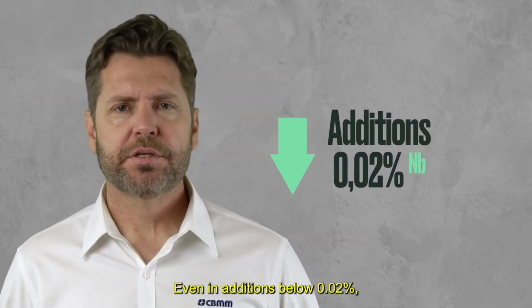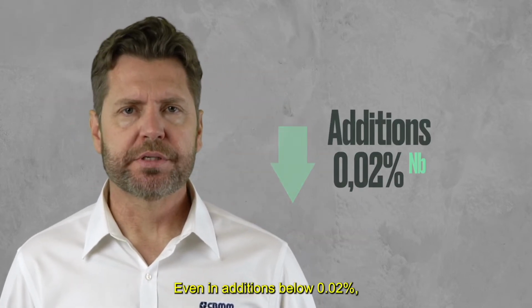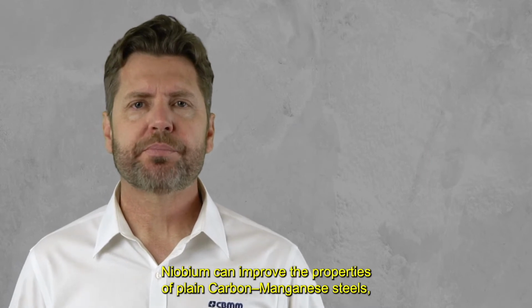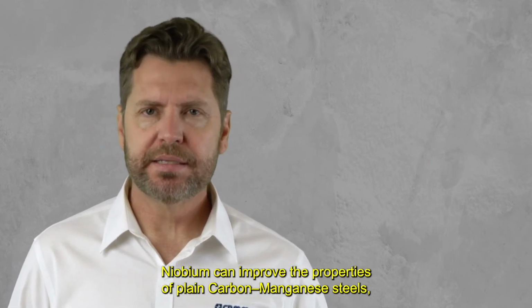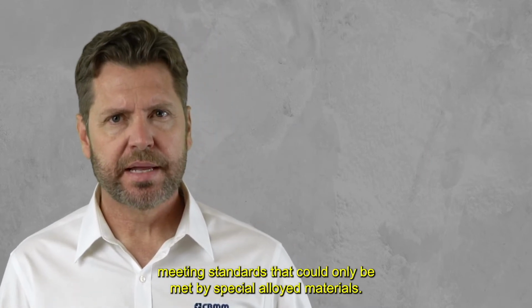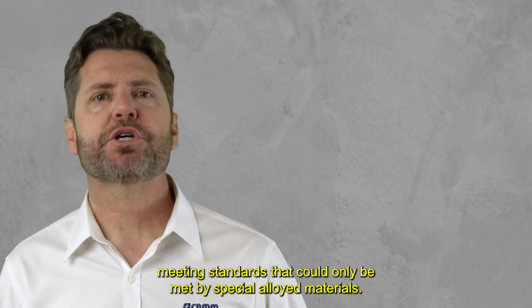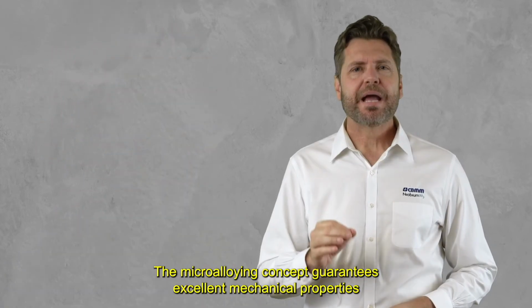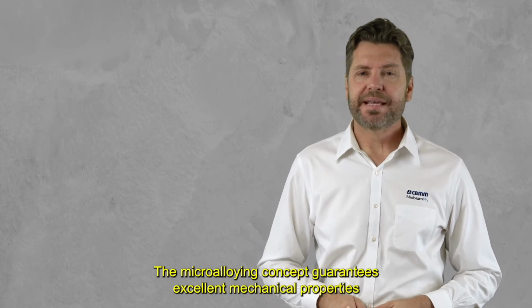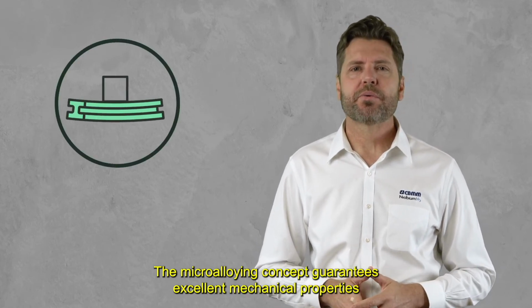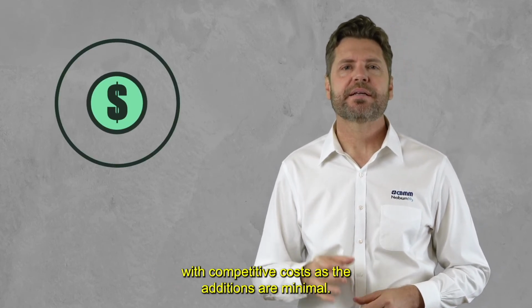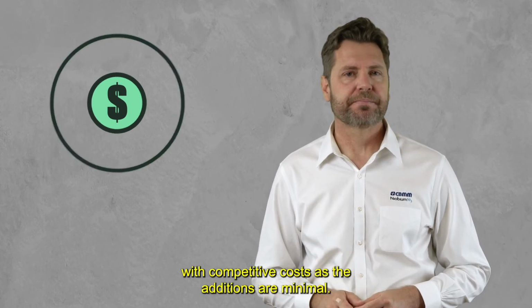Even in additions below 0.02%, niobium can improve the properties of plain carbon manganese steels, meeting standards that could only be met by special alloyed materials. The microalloying concept guarantees excellent mechanical properties with competitive costs, and the additions are minimal.